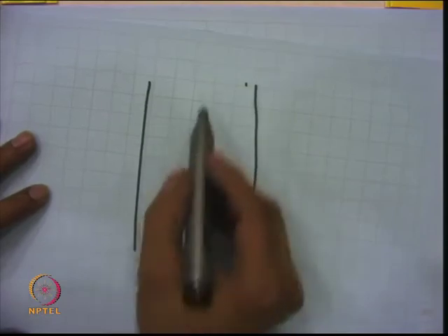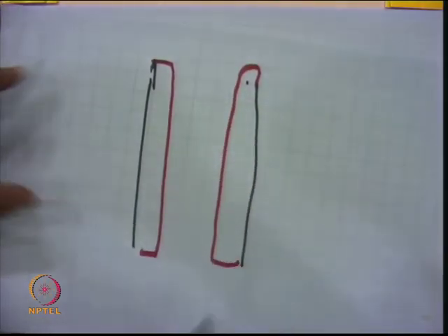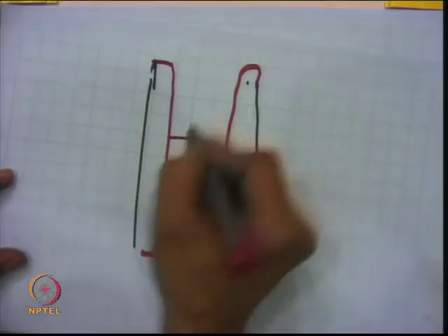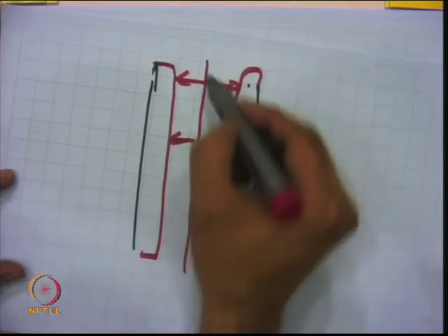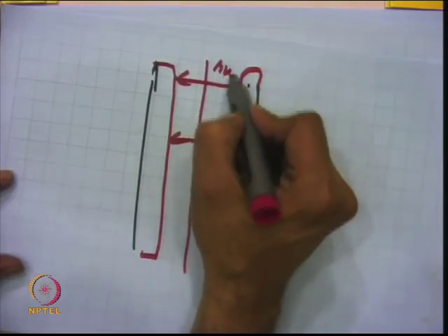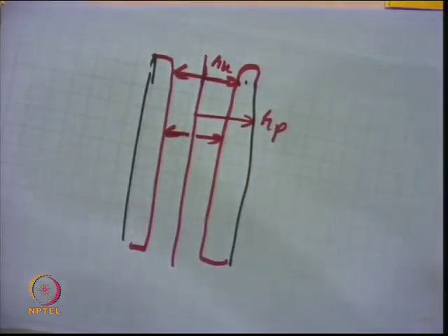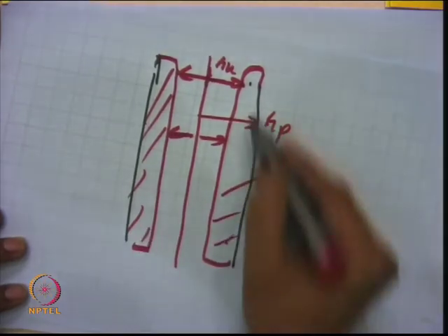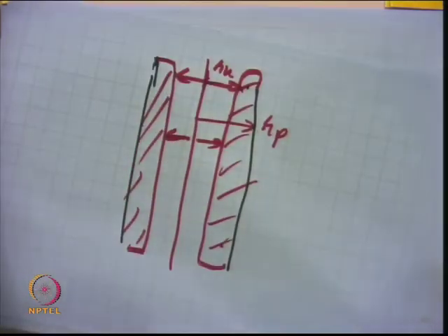Suppose this is the capillary. As I said, part of the layers are adsorbed, so they will not be available for condensation. This layer thickness is the adsorbed layer, and this is the surface where condensation and vaporization take place. What we get from the Kelvin equation, which talks about the vapor pressure of these layers, is RK, from the center to this surface, whereas the total pore radius is RP. Delta V is nothing but the volume of gas adsorbed for making the adsorbed layer. The vaporization that takes place gives you the idea of the volume of the pore vacated because of the capillary desorption phenomenon, because it is related to the vapor pressure, and vapor pressure is related to the Kelvin equation, not to the adsorbed layer.